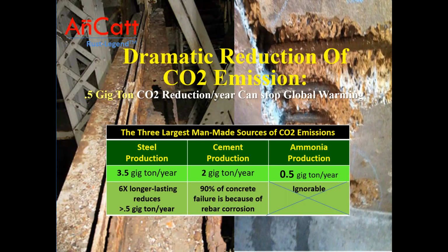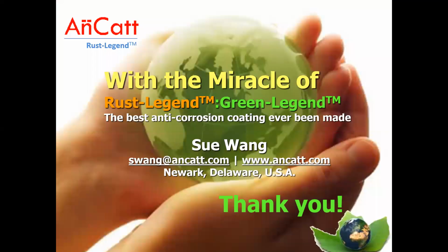Cement is used to make concrete, and 90% of concrete failure is because of corrosion of the steel rebar inside. If we could reduce the amount of steel wasted by corrosion alone, we could save enough CO2 emissions to reach the 0.5 gigaton CO2 emission reduction goal to stop global warming. With Rust Legend by Green Legend, the best anti-corrosion paint ever made. Thank you so much.